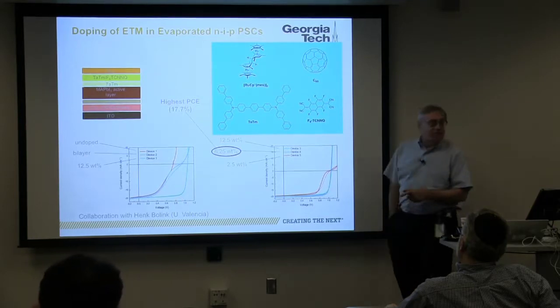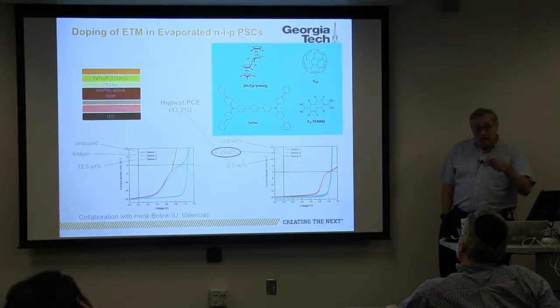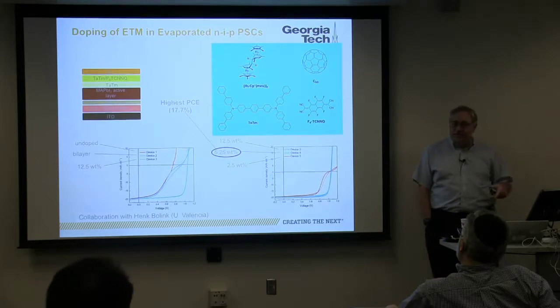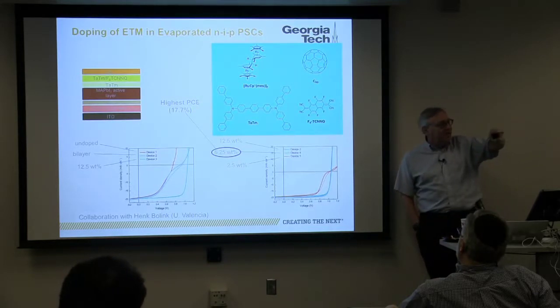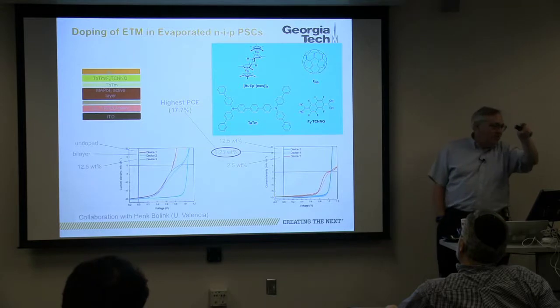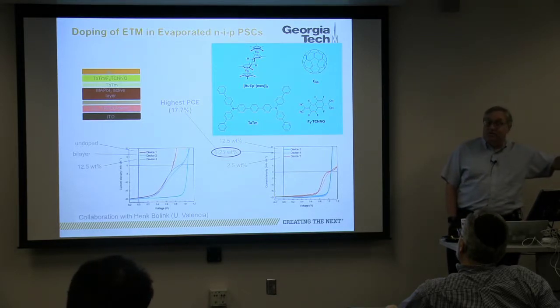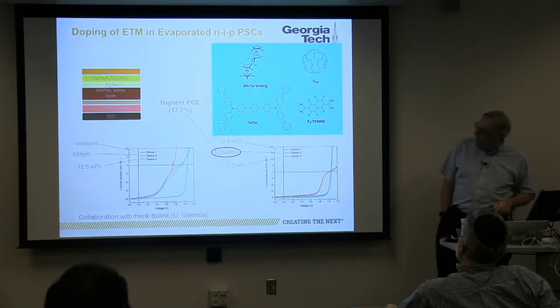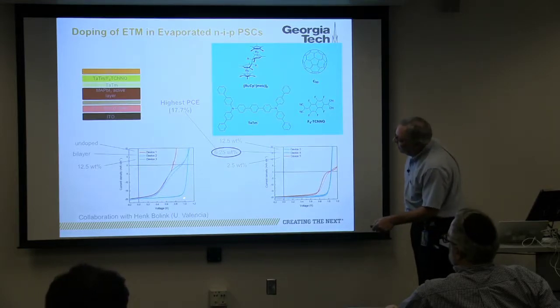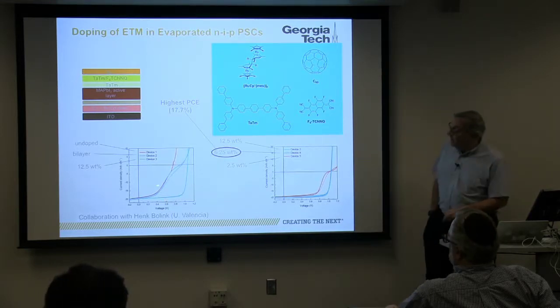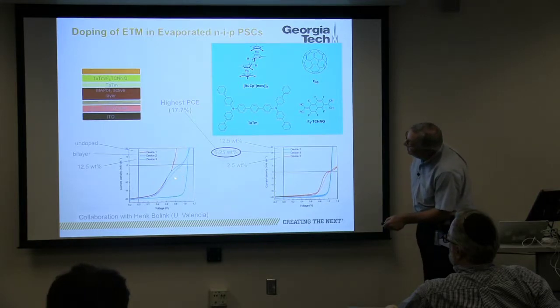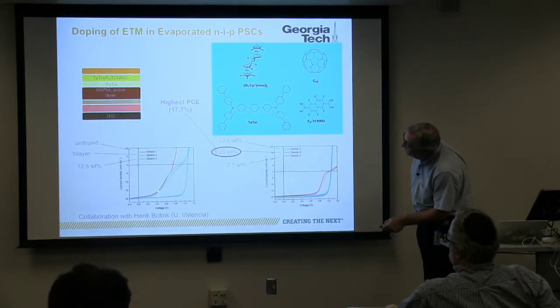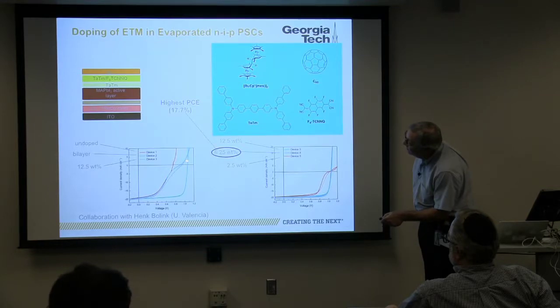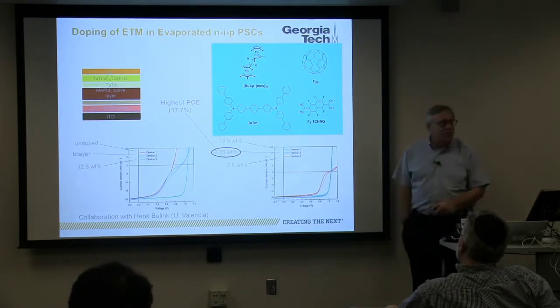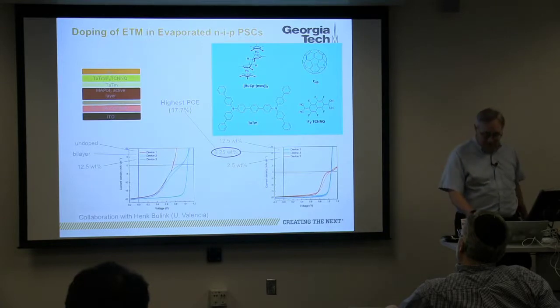And one of the things that's also important in the world of perovskites is something called hysteresis, and that is when you look at the scan going up in potential, and then you look at the scan going down in potential, they're different. And here what you are looking at is the scan going up and down in potential. Here you can see the hysteresis in the blue curve, one that goes up, one that comes down. Here they're superimposable, which means that the issue of hysteresis is not something to worry about.